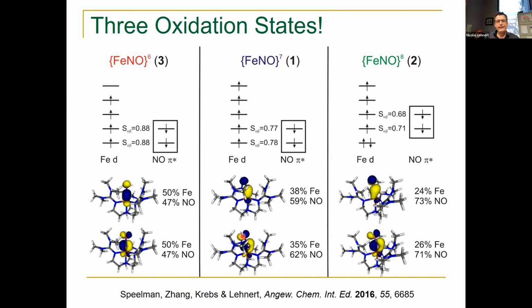So again, the FeNO7 complex being in the center, if we reduce this complex by one electron, it is actually the iron center that gets reduced. So it goes from iron-III NO- to iron-II NO-. Correspondingly, the iron-NO bond becomes less covalent, and you can see this here in the coefficients from about 35% iron mixture into the pi star orbitals, it drops to about 25%. Right? And on the other hand, if we oxidize, we go from iron-III to iron-IV NO-, and now the iron-NO bond becomes more covalent, and actually this complex is kind of at the point of maximum covalency according to the DFT calculations. And that means in this case, we have the strongest iron-NO bond and the strongest NO bond. So again, vibrational data here being key, allowing us to analyze the detailed electronic structure now of this series here of complexes.